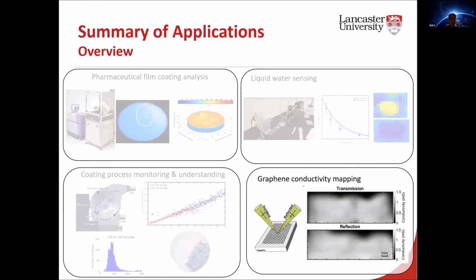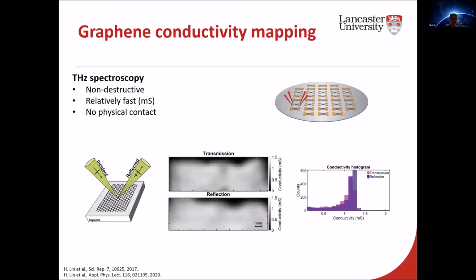Now, using other characteristics of terahertz, we can also look at mapping out the electrical conductivity of graphene over large areas. The conventional way of measuring the electrical conductivity of a sheet of graphene is that you need to make electrical devices by means of lithography. Now, as you may or may not know, this is a very time-wasting and destructive method, because once you make the devices, you then need to measure each of these devices individually, and then you throw away the wafer. So what terahertz spectroscopy has been shown to do is measure the electrical conductivity of graphene non-destructively, so you don't need to make any of these devices, relatively fast, in the order of milliseconds per point, and also with no physical contact because it's light ultimately.